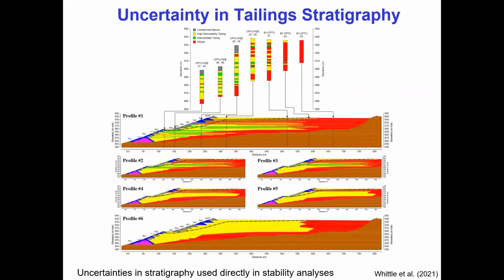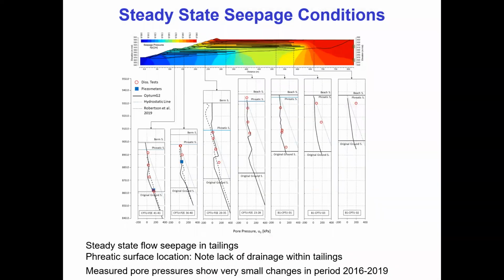So we created these uncertain stratigraphy profiles and then asked ourselves, well, what properties do we want to assign for stability analysis? The water pressures, I will spare you, but the water pressures we fit with a very simple model. The different layers, of course, have different hydraulic conductivity, so that they affect the results. The model fits rather well the measured data, I think, is the method. Something very interesting they did here, they measured water pressures from the dissipation of piezocones. So they also have water pressures at the time the piezocones were taken, which is also a useful piece of data.